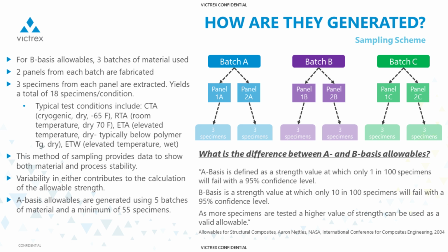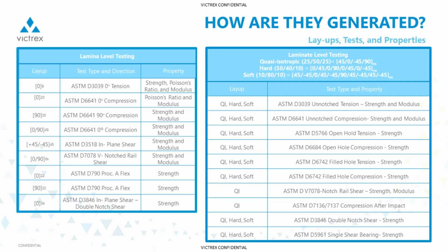The program I just described is for B-basis allowables, but if you want to have A-basis allowables, which are defined as strength values where only 1 in 100 specimens will fail below a value, a minimum of 5 batches of material are used and a minimum of 55 specimens per test. For B-basis allowable programs, the strength value calculated is a value at which only 10 in 100 specimens will fail below that value.